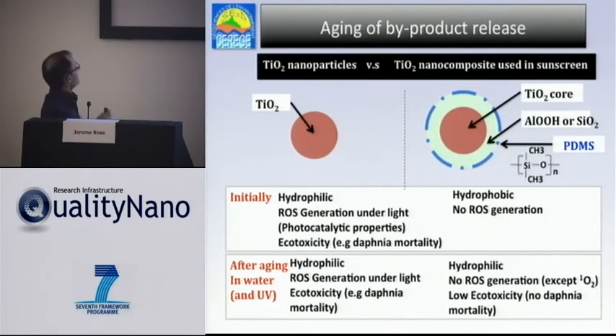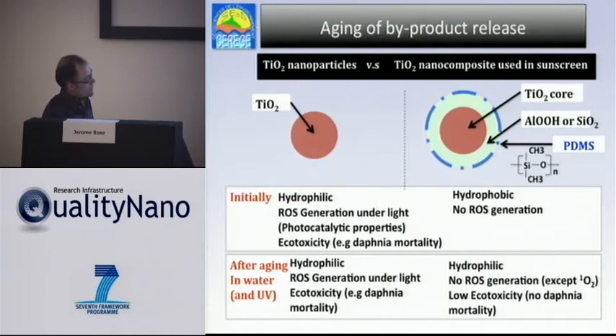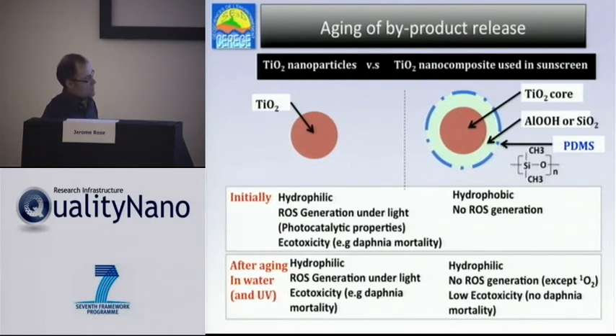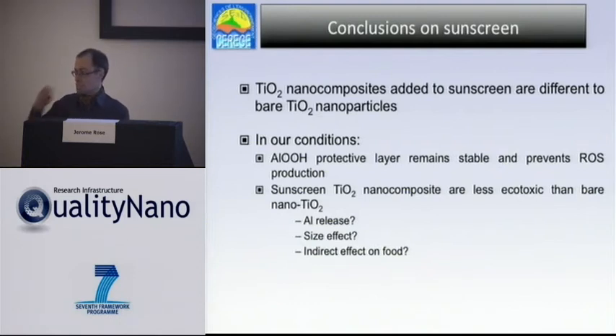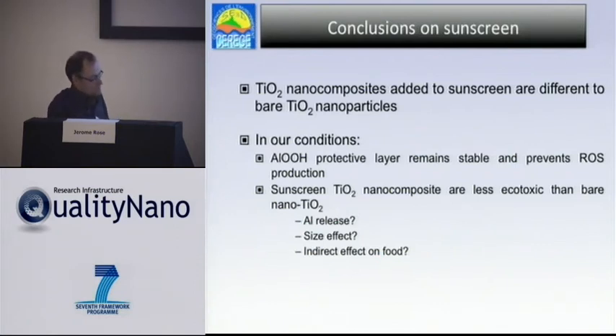As a summary of this sunscreen work: initially, the compound can be very different in terms of properties — hydrophobic, no ROS generation. After aging in water, they can change in terms of dispersion size and properties — becoming hydrophilic. Since the aluminum layer still remains and still protects, the toxicity seems to be very low compared to bare nanoparticles. The initial question was: can we extrapolate results from bare particles to particles that are in the commercial product? The answer, unfortunately, is no in this case.